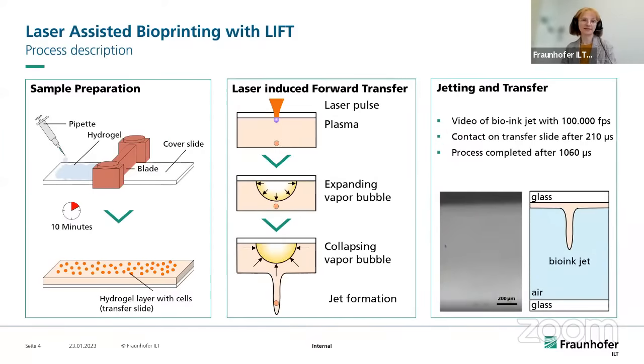The laser printing process itself works as it is described here. First, we have to prepare a sample where all our cells are presented in a hydrogel layer. Then we put it upside down, and have a laser pulse coming from the top, focused to the edge between the glass and the hydrogel. A short laser pulse in the range of 10 nanoseconds induces a water gas bubble, and when this gas bubble collapses, a jet is built, as you can see here in this video. Such a jet has a duration of nearly 200 microseconds up until it contacts the other side, and it depends on the laser power we are using here. So you can imagine that we have a rather fast process.